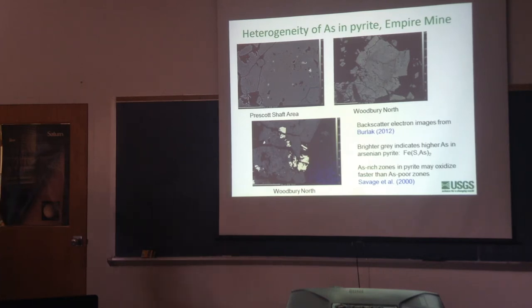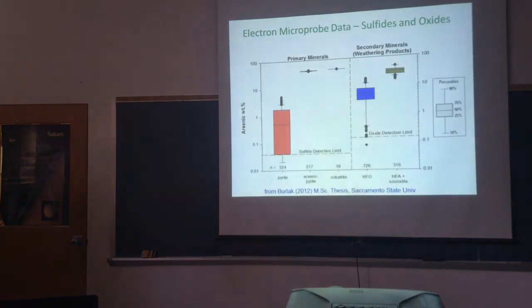One thing we learned from the literature is that the arsenic content of pyrite can affect how fast it oxidizes. It's basically the arsenic-rich zones have more defects, and they're more susceptible to rapid oxidation. So that's a factor in trying to understand the weathering history, that maybe the zones that have higher arsenic will erode faster and liberate arsenic more rapidly and at a higher percentage than was originally in the material.